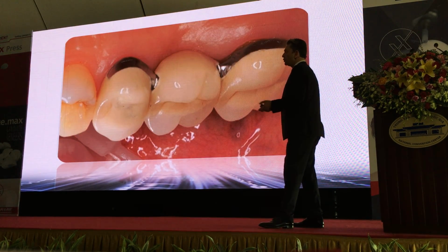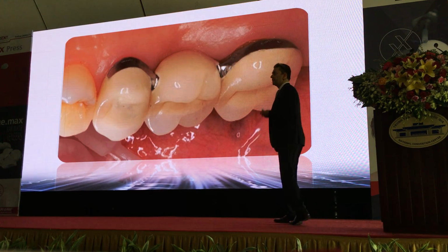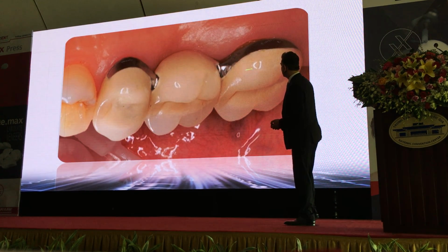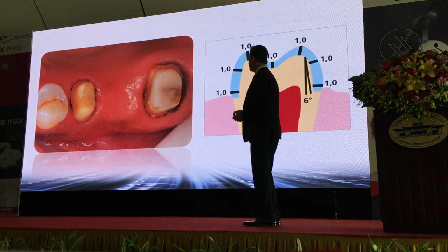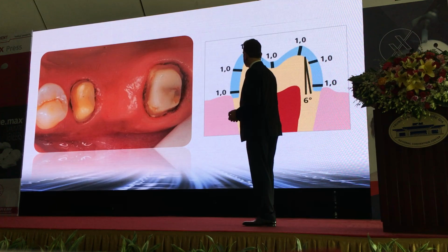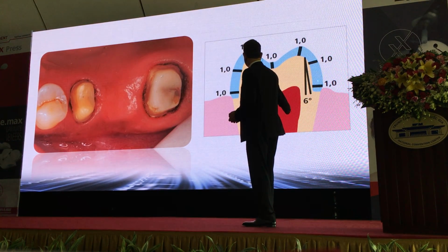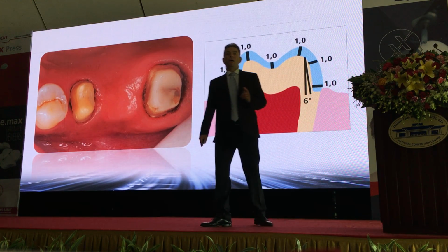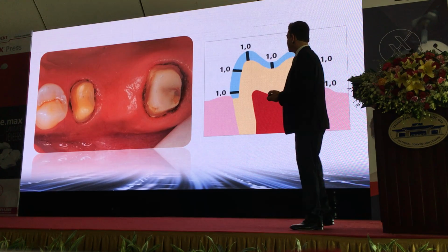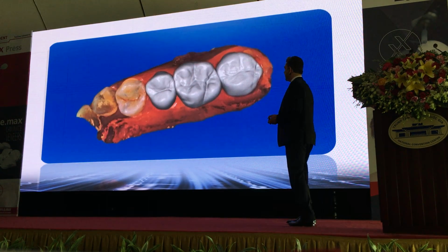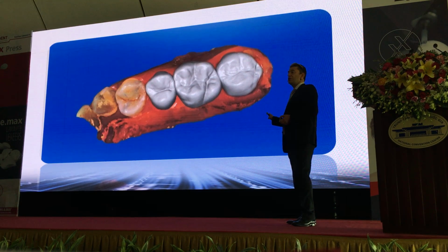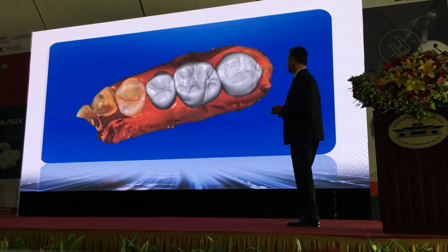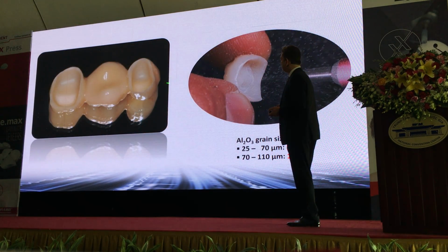Okay, so now I would like to go a little bit through some clinical cases. You can see here a molar bridge, a PFM bridge. So if you remove the restoration, you can see now with the new material, with the MT Multi, we need to have 1 millimeter of thickness for the bridge with the multicolor zirconia. Then we can design this in the software, so this one at the chairside. But you can always order these kinds of restorations from your lab if you don't have a chairside system. You can see now this has been milled and stained and glazed.